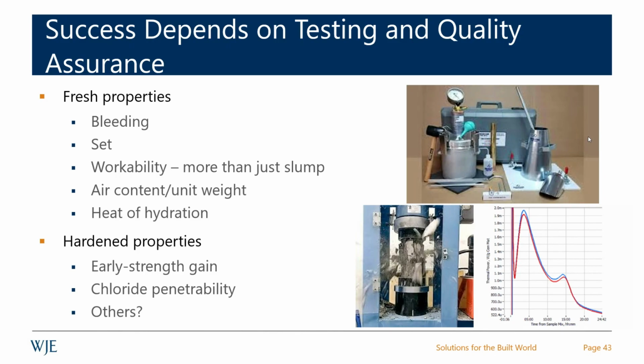But regardless, we are seeing some fluctuating air content, so I really encourage you to watch that and also start measuring unit weight in the field. It's a very simple test to do. You just need a scale, and that's a real good indicator if your air is getting high. And then heat of hydration is something that you might want to start looking more at.